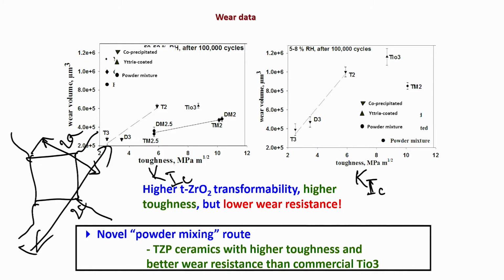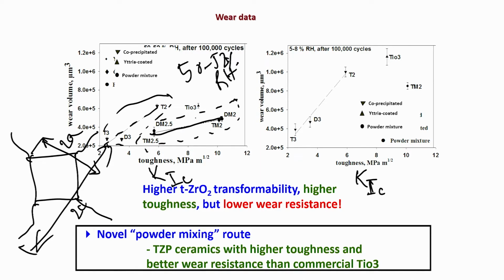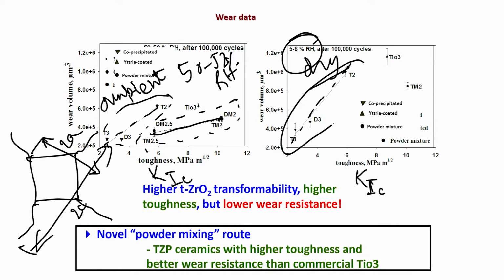Now, what you see is that wear volume increases as you increase the fracture toughness. That is true for ceramics made from commercial powders. From our own powders, like powder mixtures TM 2.5, TM 2 and so on, you again see an increasing trend of wear volume with fracture toughness. This is not only true for 50 to 52% RH, that is relative humidity, the ambient conditions, but also under dry conditions. Dry conditions are again 5 to 8% relative humidity, and you again see that fracture toughness increases from T3, D3 to T2, and that leads to an increase in the wear volume.